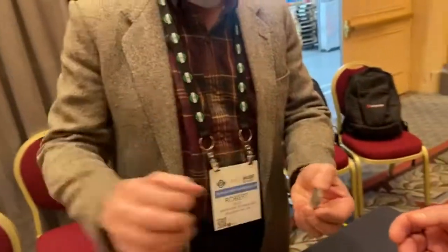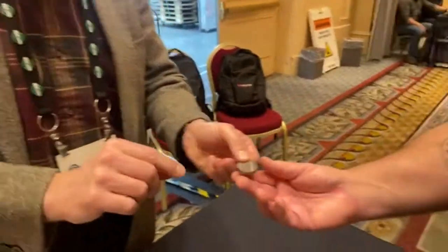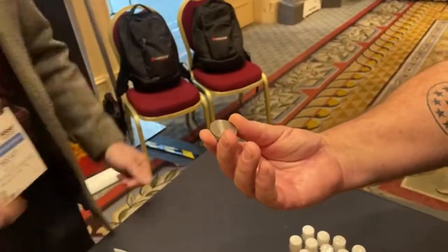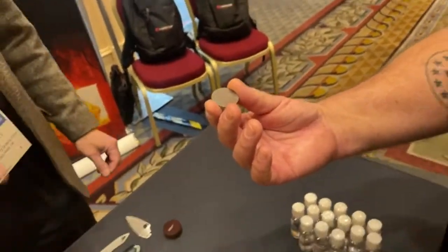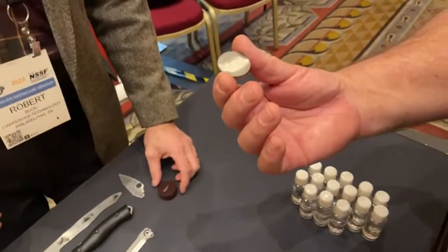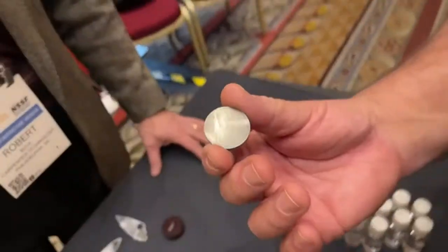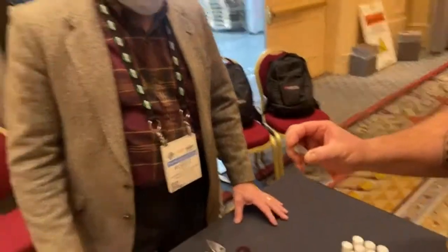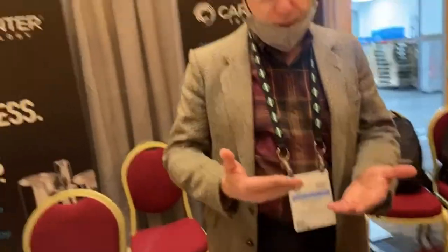In fact, I don't know how good your eyes are, but if you look carefully around the perimeter, this was a 1-inch bar that we carburized. You'll see about a 2 millimeter hard case. I see it. Yeah, so that's what we do both for bolts, bolt carriers. We can also carburize barrels. So you get that super hard outer layer.